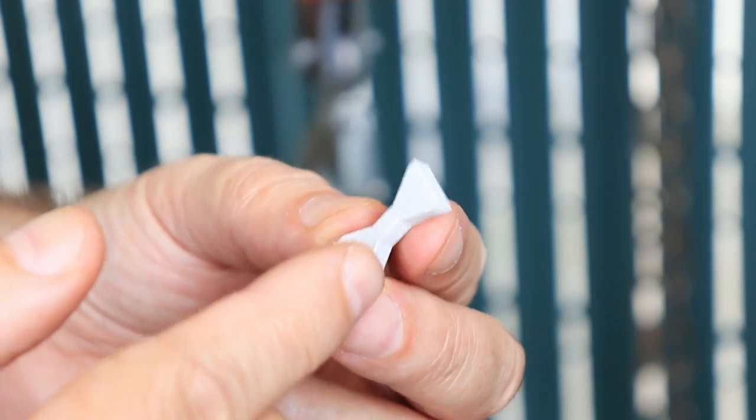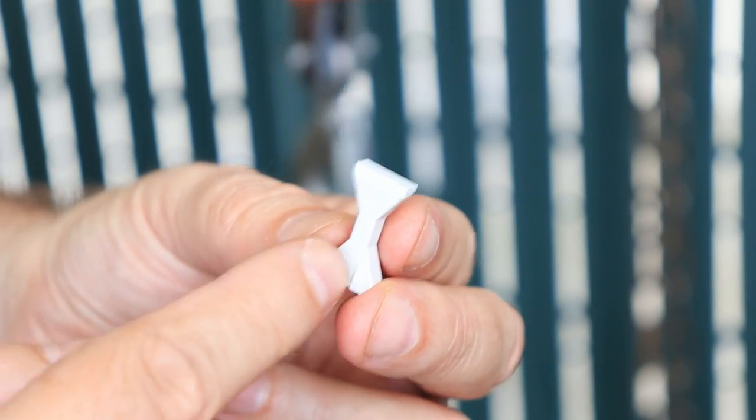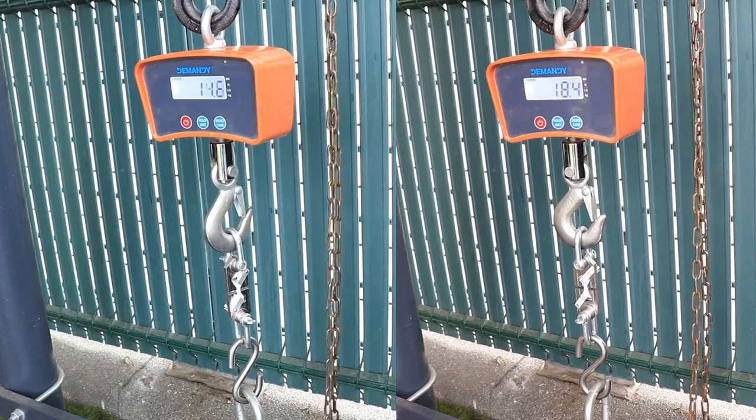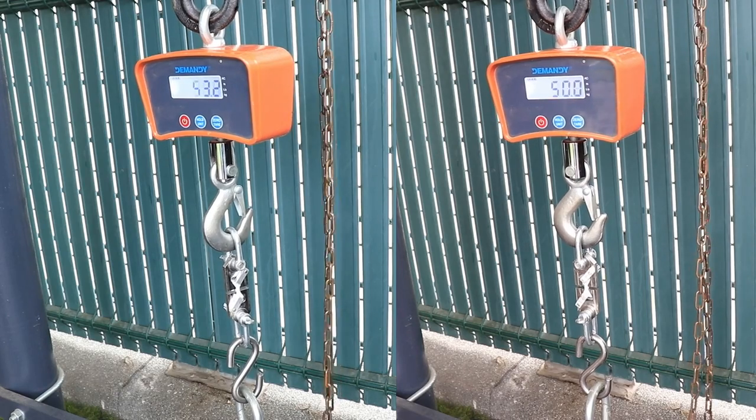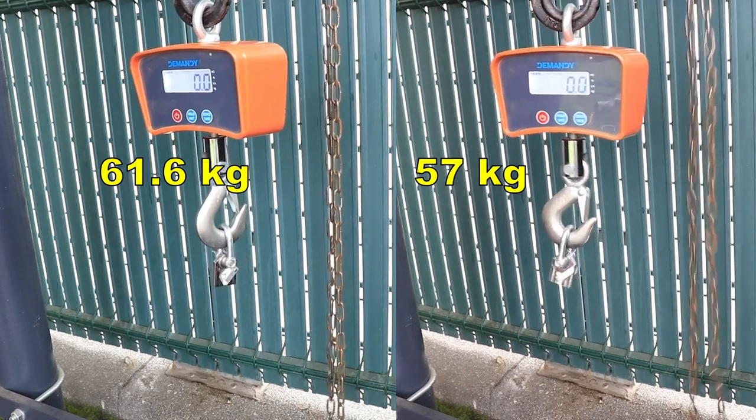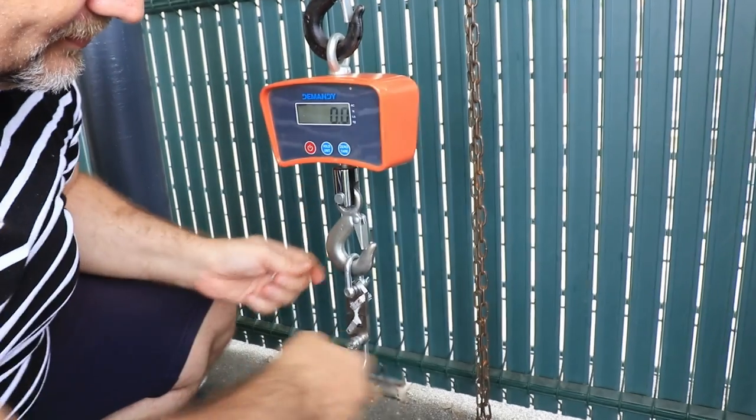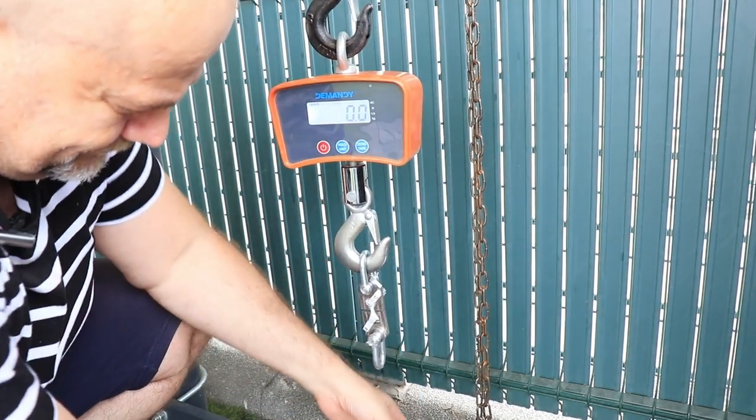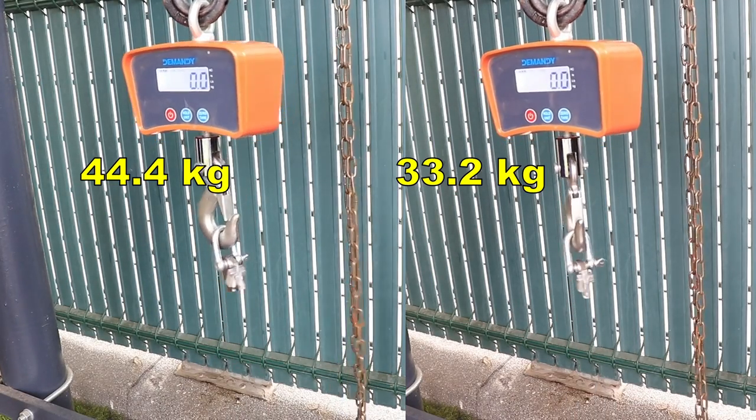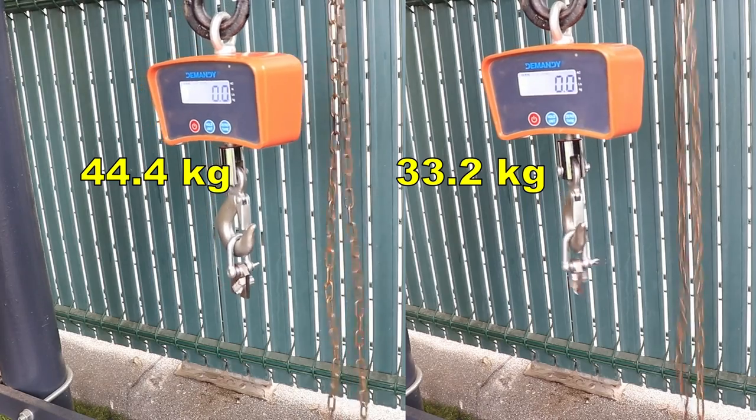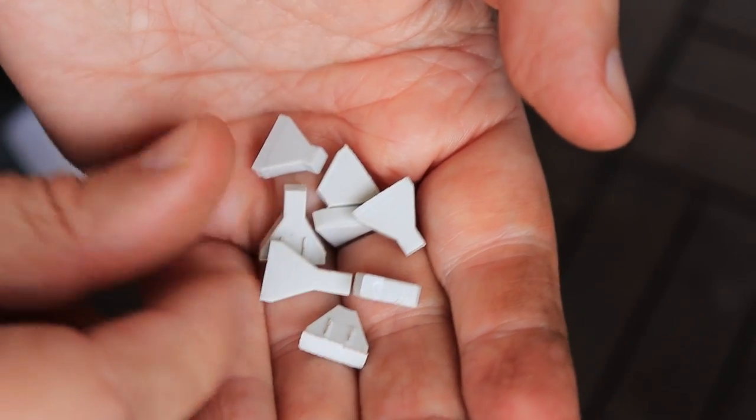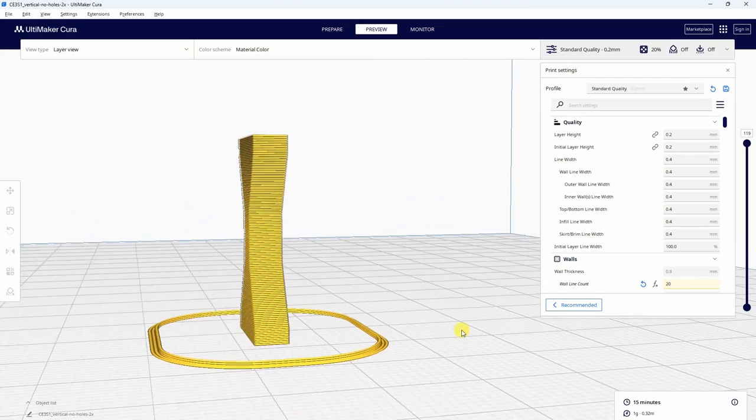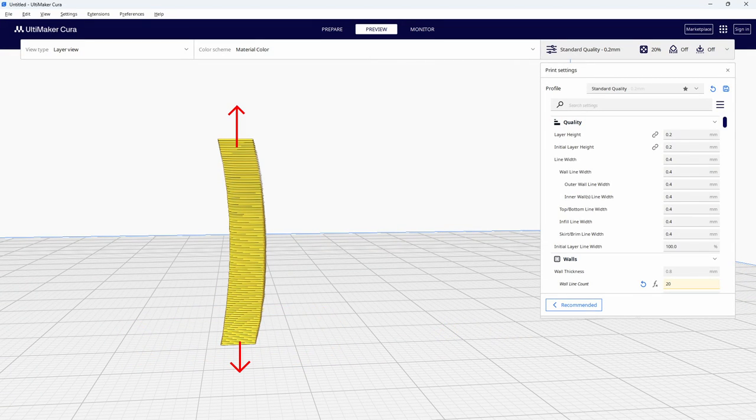And now let's check the layered version with vertically printed objects. And I am starting with the regular PLA. And now annealing version. And again very similar breaks in all four cases. Now I noticed some warping on these objects too. So in holder was under small angle, and this could be the reason for the lower break load.